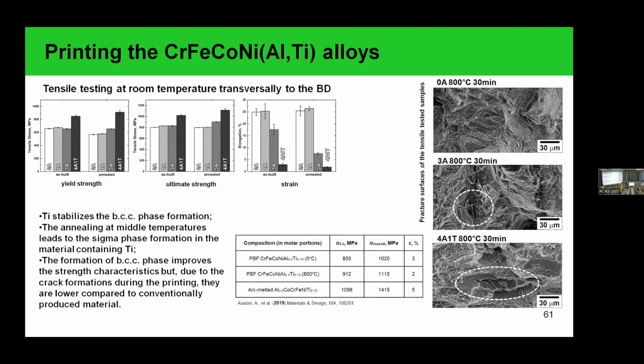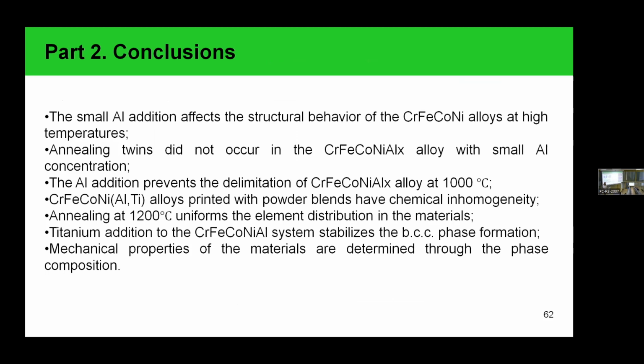we still have low ductility of our material, even lower than for the arc melted material, and we also observed lower strength in comparison with arc melted materials. It can be a result of the hot tears which are formed during the printing process, and for the further application of this approach of printing in situ, it is a challenge. In the printed materials, several phases are formed and the inhomogeneous material should be solved.